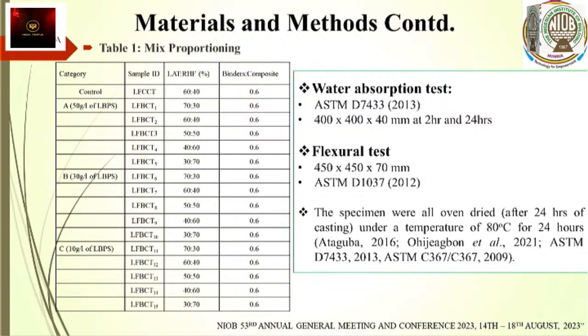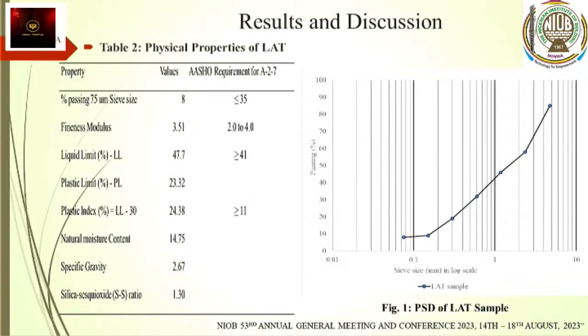to established literatures. Then the results, before we look at the tile itself, we had a look at the properties of the laterite, and we need to be sure it conforms to a classification of AASHTO. And from that, we found that it can be classified as an A2-7 laterite. What do I mean by that? There are properties expected. One of them is percentage passing 75 micrometer sieve, which must not be greater than 35%. In this work, it was 8% that passes.